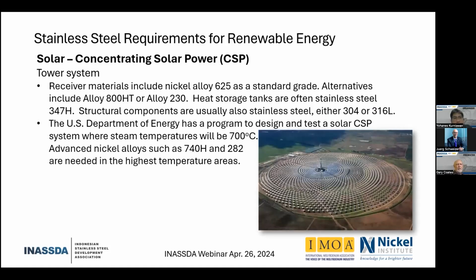The receiver materials are typically a nickel alloy, the 625 with 9% molybdenum is the standard grade. They can sometimes use a lower alloy material, the 800, which is actually classified as a stainless steel in the North American classification, although we think of it often as a nickel alloy, or alloy 230, which is a true nickel alloy.